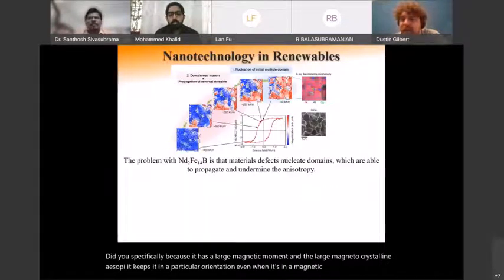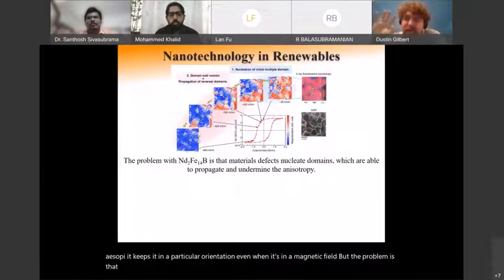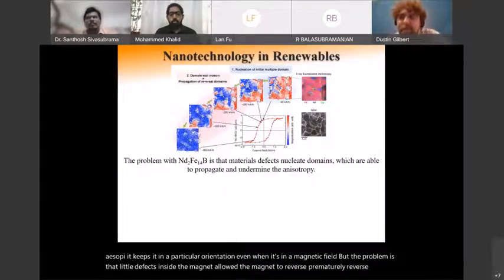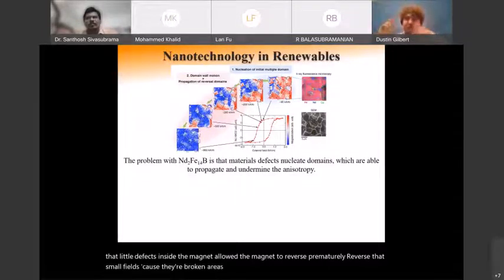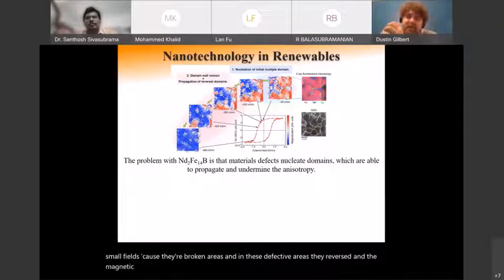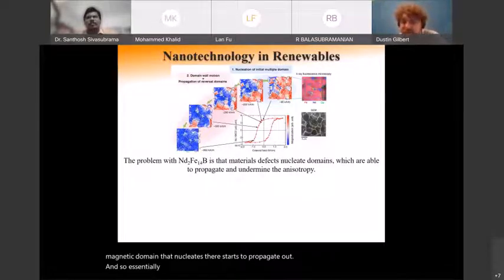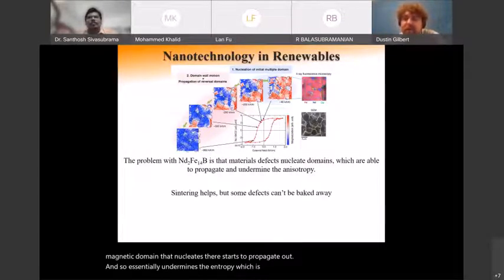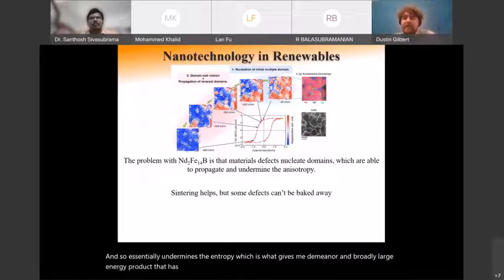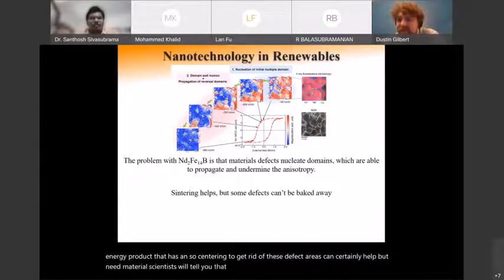But the problem is that little itty bitty defects inside the magnet allow the magnet to reverse prematurely, reverse at small fields, because they're broken areas. And in these defective areas, they reverse, and the magnetic domain that nucleates there starts to propagate out. And so it essentially undermines the anisotropy, which is what gives neodymium iron boron the large energy product that it has. And so sintering to get rid of these defect areas can certainly help, but any material scientist will tell you that sintering materials doesn't get rid of every defect. It gets rid of some, but there are plenty that are still left that cannot just be simply sintered away.